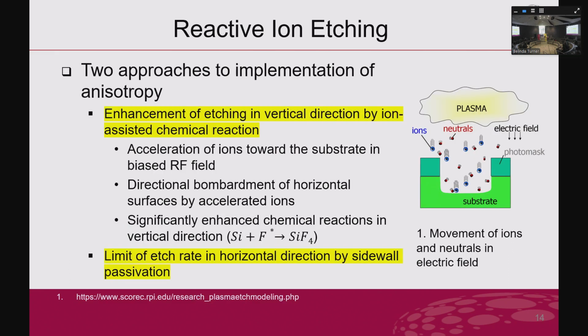During the RIE, two approaches happen at the same time. First is the vertical direction I am bombarding, especially, like I said, we have the electric field to control it, and then we rely on the reaction of the ion with the substrate. I put silicon here with the fluoride. With this dry etching, we call RIE etching, there are different types of process gas. So here I use silicon as an example. The silicon and the fluoride will form silicon tetrafluoride gas, a byproduct that comes out and then is removed during the process. Also we have the sidewall passivation gas, so that's why it doesn't really attack the sidewall.